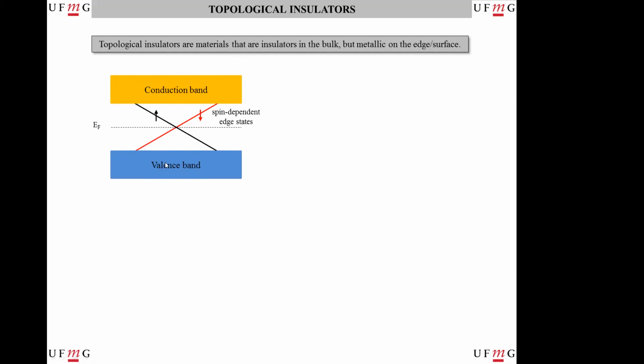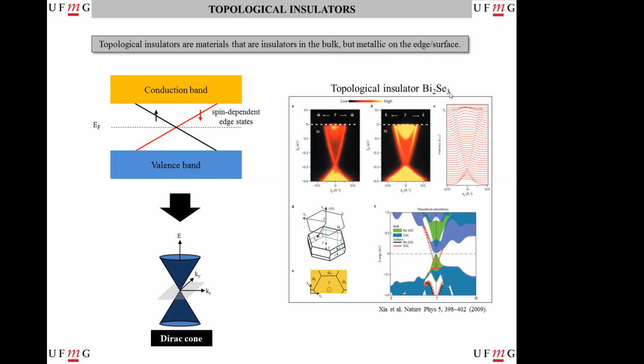And if we look at different positions of momentum, we can see that for a 3D crystal, we have 2D states, and they form what we call the Dirac cone. These states here, when we rotate, form the Dirac cone. And the Dirac cone is the signature of the topological insulators. Here we have, for example, the best-known topological insulator, which is Bismuth Selenide. Here we have theoretical calculations of the bands of the material, with the states crossing the band gap, and here we have ARPES images of the same structure.